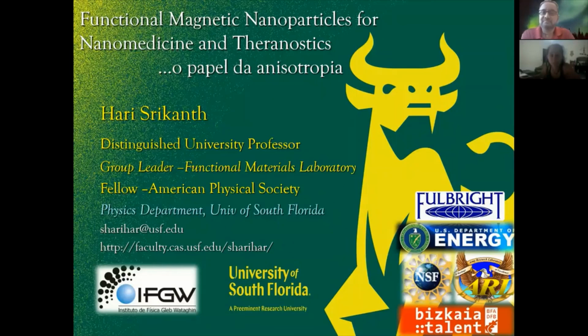Okay. Professor, thank you very much for the nice, interesting talk on magnetic hyperthermia. You have shown a lot of results on the anisotropy effects on the heating behavior. I would like to know, you have shown the exchange-coupled nanoparticles like FeO and Fe3O4 of different shapes, spheres, cubes, and octopods, and also other shapes. How does their anisotropy affect the heating behavior? Have you quantified the anisotropy through the RF-TDO method?